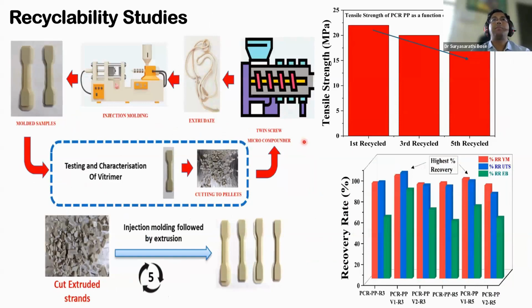So since this talk is all about emerging solutions for recycling, we put our material to test. And we did this exercise for 5 times where we extruded, we molded, we cut them into pieces, we put them in the extruder, and we repeated this cycle for 5 times. If you do this exercise for the PCR olefin straight away from the market, you would see that the tensile strength drops significantly with each recycling sequence. The MFI shoots up with every recycling sequence.